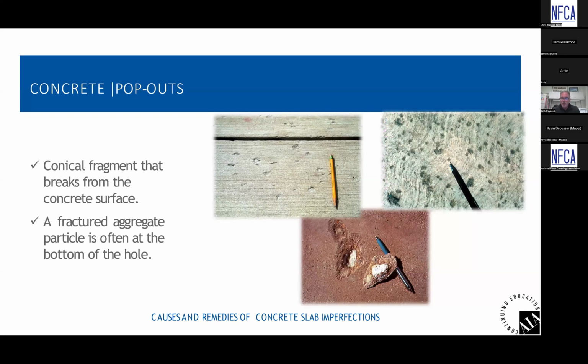They should be using materials that don't affect concrete, but unfortunately, we see in the States here that they sell regular old rock salt all the time at the big box stores, and that's detrimental to concrete and can cause pop outs. In essence, if you're seeing pop outs like this, interior or exterior, again, raise the red flag. In some cases, they have to take a core sample to confirm what the cause of the pop out is. We just all know that concrete should not have pop outs like this. So we need to raise the flag and confirm what the cause is, and then once that's done, offer a means for remediation, depending on what the cause is.